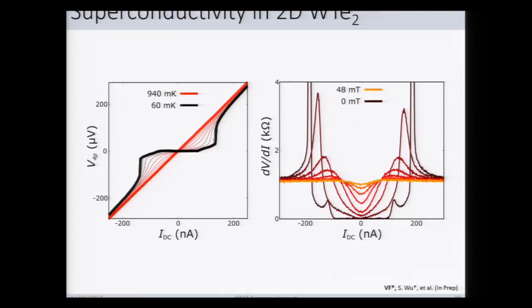Instead of a VI curve, we can do the differential resistance. This critical current now appears as a sharp peak. And as we increase the magnetic field, we see that we remove the nonlinearity and again return to a simple metallic state, again showing that, as expected, magnetic fields kill the superconducting state.